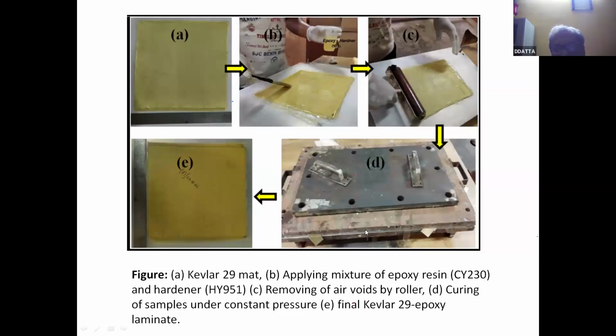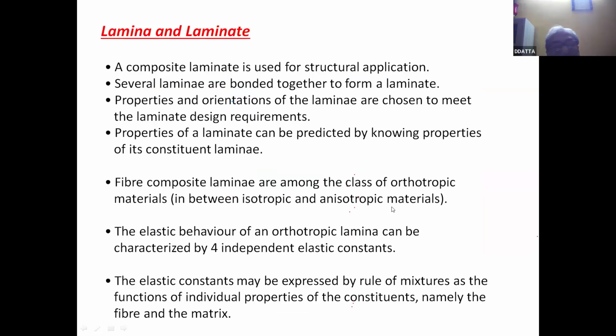It can be done with heating or without heating, but sufficient pressure is to be applied. And to keep the thickness of the laminate uniform in all portions, we need to put in spacers depending on the number of plies that have been laid. Finally, after curing, we get the final laminate. Here the ply is a Kevlar 29 ply cut from Kevlar 29 mat, and the mixture is epoxy resin and hardener.